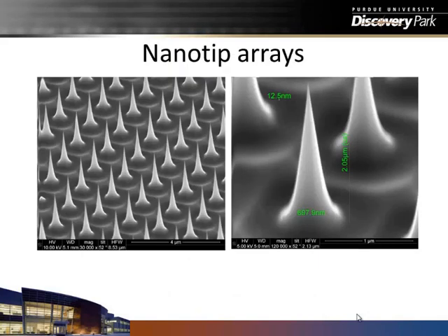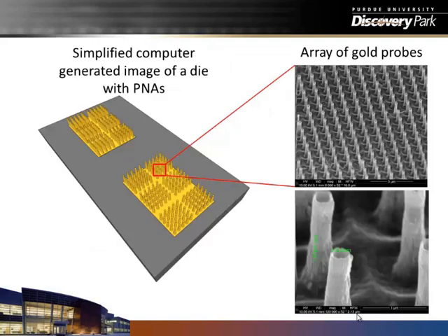These are some pictures from fabrication. These are the sharp tips that we make in silicon that form the basis of the mold. These are about 2 micrometers high, about 10 nanometers in tip. And we can control this thickness of the tip, as you'll see downstream. This is a computer-generated image, simplified, showing what our electrode looks like on the business end, really.